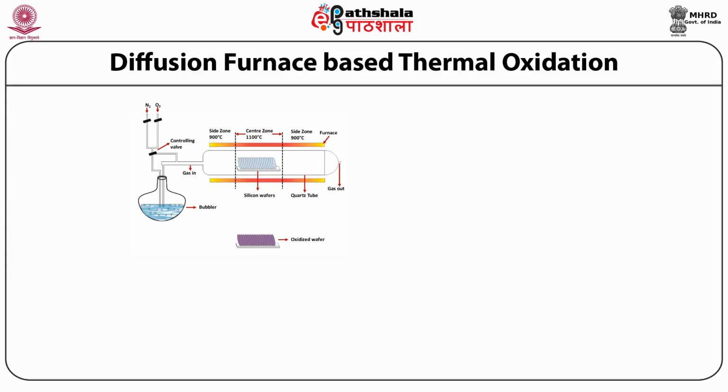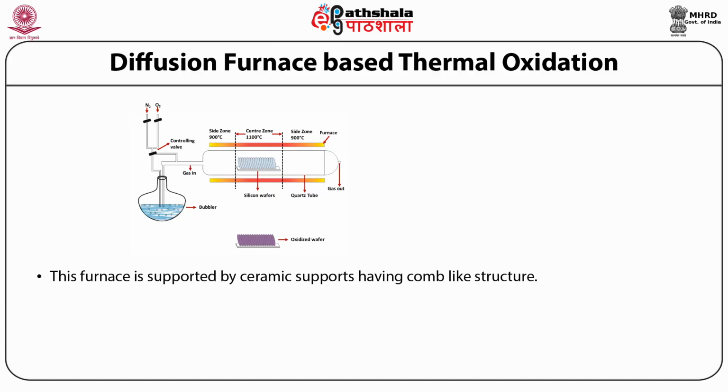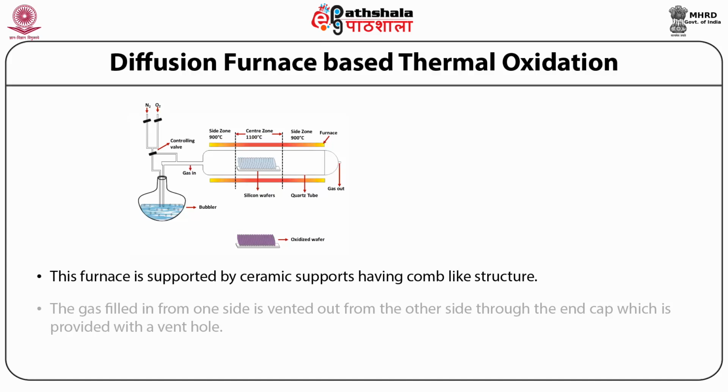This furnace is surrounded by resistance heaters, which produce the heating effect and are coupled with thermocouples to monitor this heating. This furnace is supported by ceramic supports having comb-like structure. The gas filled in from one side is vented out from the other side through the end cap, which is provided with a vent hole.